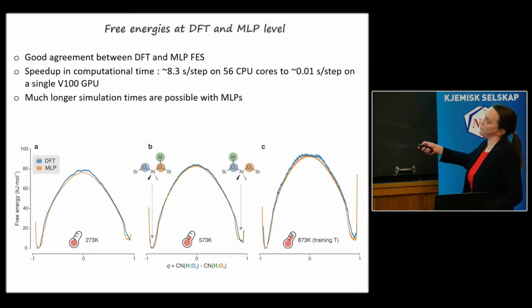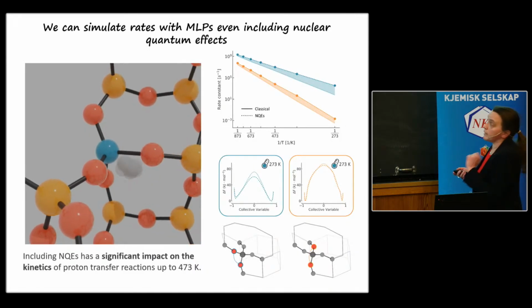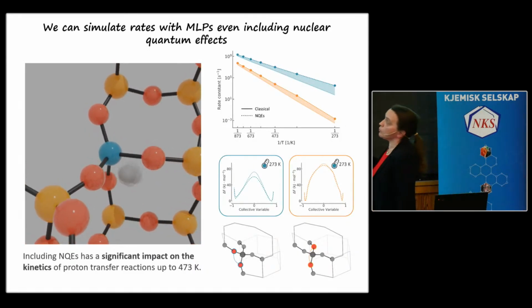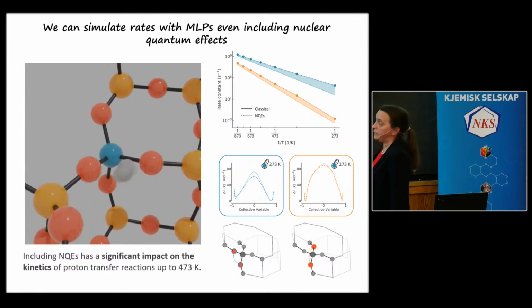And so here you can see free energies in terms of the reaction coordinate, so for these proton hoppings. And these are with DFT. The blue curves are with DFT at various temperatures, you can see. We can see that the MLP gives almost completely the same results. And then we can do the movie again. So this is now the movie which is done with the MLPs.